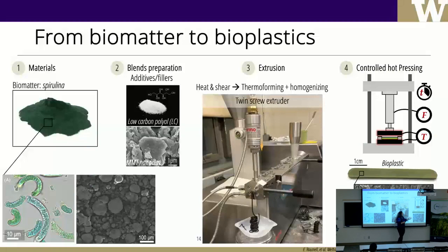And then we also, if we want to make beams for mechanical testing or whatnot, we would have to also hot press different beams. So what we want to be seeing in this case is the SEM image of the hot pressed material and the SEM image of the material that we started from. And that's just from the application of heat and pressure. You can see that here you have a homogeneous mixture, basically, of polymers, but there is no phase separation.